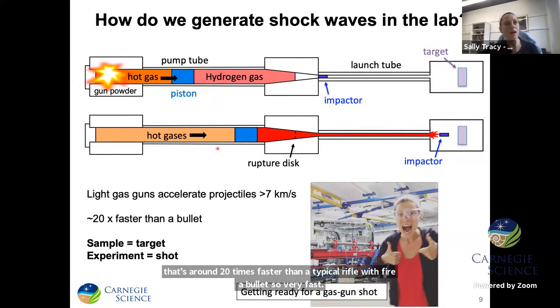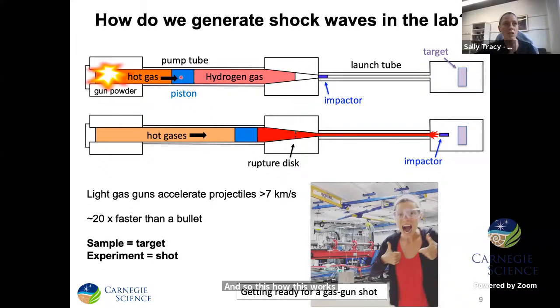And so how this works is that we have a charge detonation, and that drives our piston into a gas-filled pump tube, which is filled with a light gas, either helium or hydrogen. And that gas is then compressed to some threshold pressure, at which point you have a rupture disk that bursts, and that rupture just separates the gas-filled pump tube from an evacuated launch tube. And when that gas then expands into the launch tube, it launches an impactor, which is accelerated down the barrel to high velocities and then strikes our sample in the target chamber.